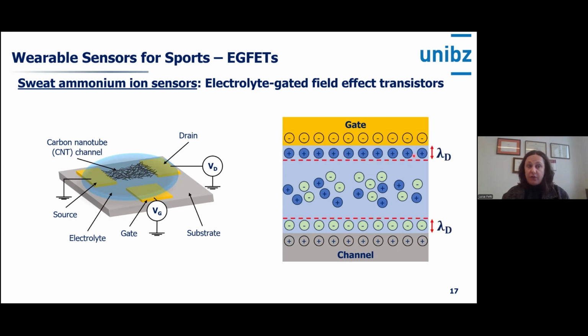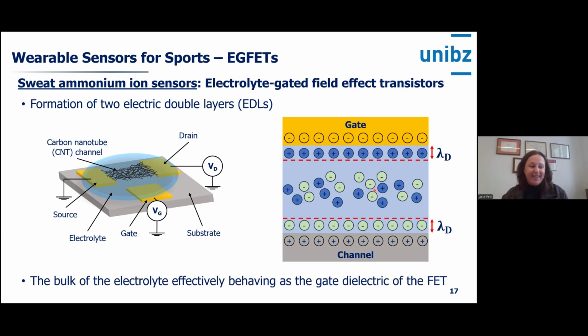Now, this leads to the creation of the so-called Debye length. So we form two electric double layers, one at the interface between the gate and the electrolyte, and the other at the interface between the semiconductor and the electrolyte. What happens basically is that the bulk of the electrolyte behaves like a gate dielectric. It's clearly not a gate dielectric, but there is basically no conduction anymore in the bulk, and you have interesting effects at the two interfaces, at the Debye length.